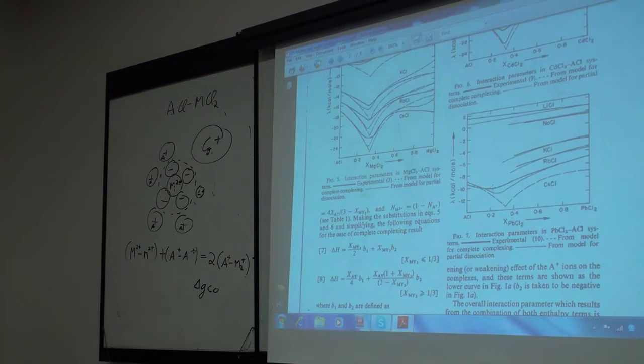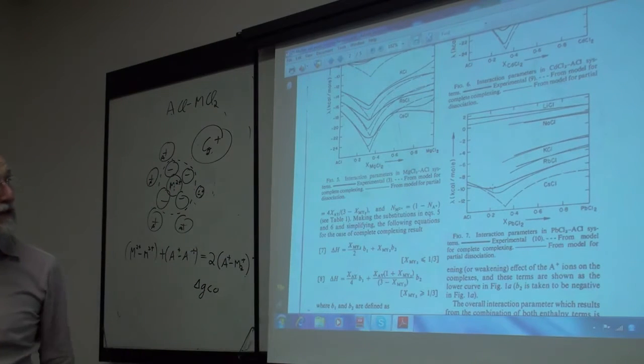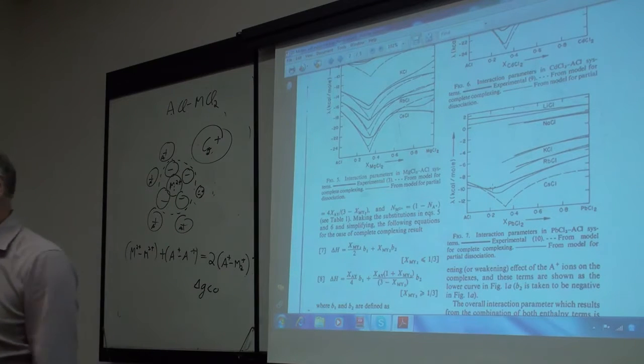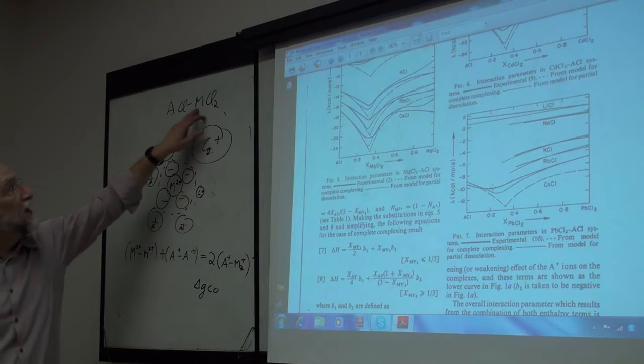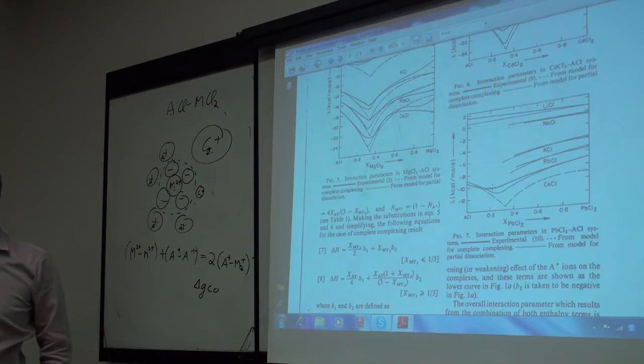As soon as you get down to calcium, down in the alkaline earths, you really get very little complexing. Maybe a little bit if you take alkali chloride, calcium chloride, I don't have them on here, but calcium chloride, alkali chloride, even with cesium, tends to be pretty close to a random type mixture. But certainly strontium and barium don't have any real complexing effects. Okay, so as this M2 plus ion gets bigger, the tendency to the complexing decreases.